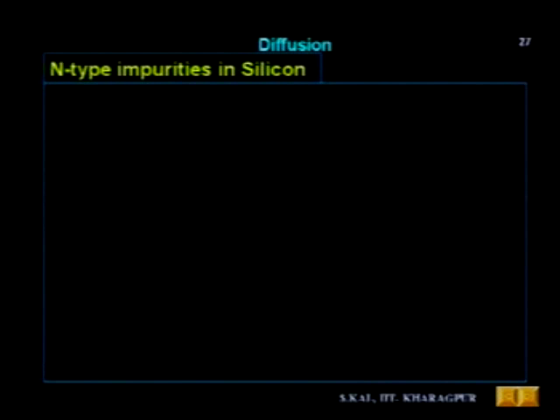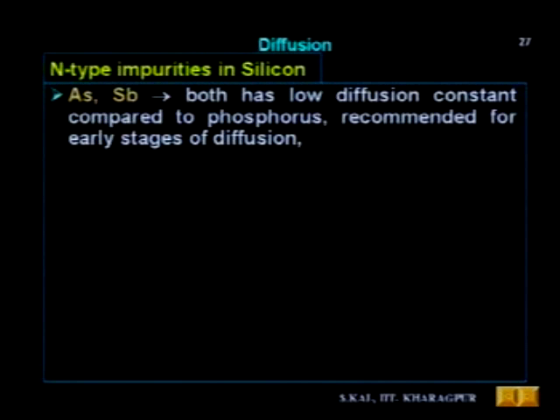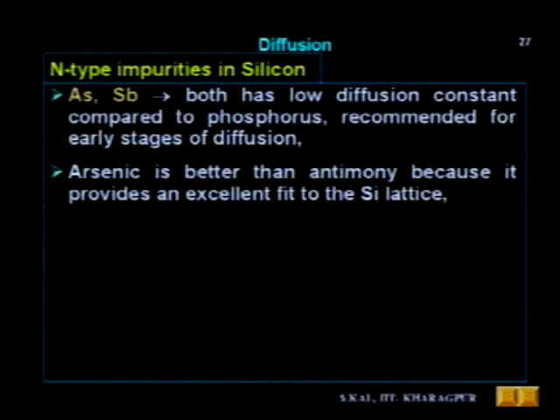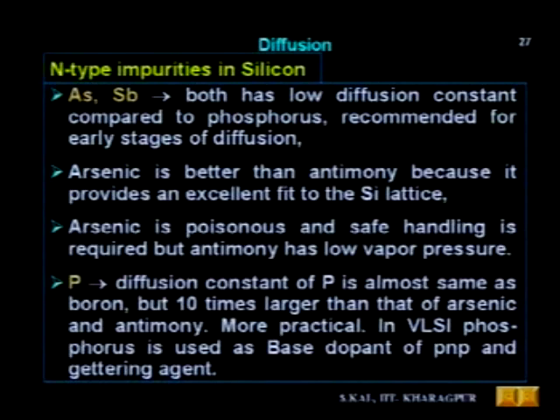Now we will discuss n-type impurities in silicon. The n-type impurities in silicon are antimony, arsenic, and phosphorus. These 3 dopants are popular for converting the silicon layer into n-type. Out of these, if we look into the details of arsenic and antimony, we will find that in some cases one has some advantage, and in other cases the other has another advantage. Both arsenic and antimony have a low diffusion constant compared to phosphorus, and a low diffusion constant has certain advantages also.